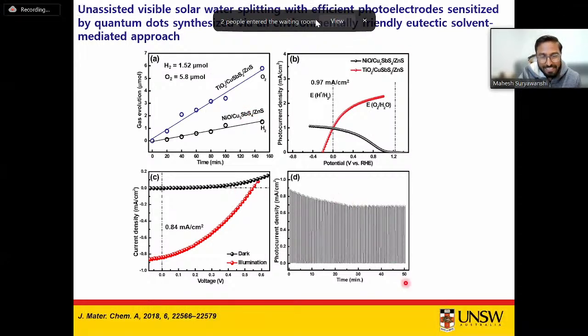Okay, so again, just another quick one. So if you see, again, these are the chalcogenide compounds, chalcogenide semiconductors. So if you see the stability, the performance goes down immediately after 1 hour of reaction, right? So that means even though we have demonstrated this kind of system, the photoelectrodes are still not so stable in the aqueous electrolyte.